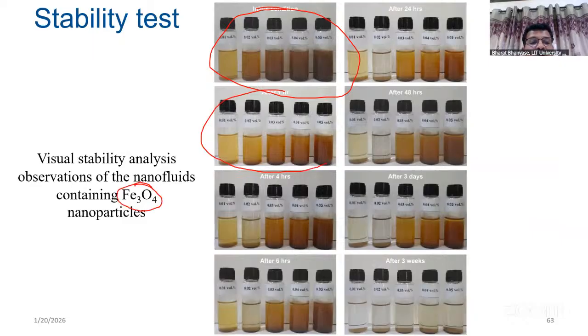This is for the case of only Fe3O4, which is dispersed in water, that is water-based Fe3O4 nanofluid. Then settling continues after 24 hours. You can observe this, and then, but after 3 weeks, complete settling was observed. So that's why you can say Fe3O4 nanoparticles, even if it is in smaller size, its stability after maybe 24 hours or like that, so that gets decreased.